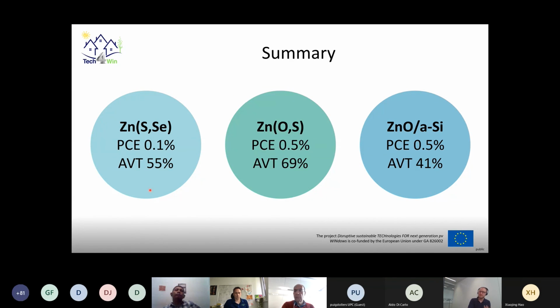So to summarize, in TECH4WIN, we are working on chalcogenide and oxide-based approaches for fully transparent UV-selective and UV-filtering PV devices. So we're aiming for very high band gaps, above 2.7 electron volts. In the case of the zinc sulfide selenide, we have been achieving a first efficiency, having also an AVT of 55%, having some issues typically with hole formation in the layers. But if we could solve that, basically bringing in charge transport layers, we should be able to increase the efficiency, which we already did for the zinc oxysulfide, where we had the best efficiency of 0.5%, thanks to the use of the C60 charge transport layer, which we are still improving further by playing with the charge transport layers and also bringing in ALD for the zinc oxysulfide.